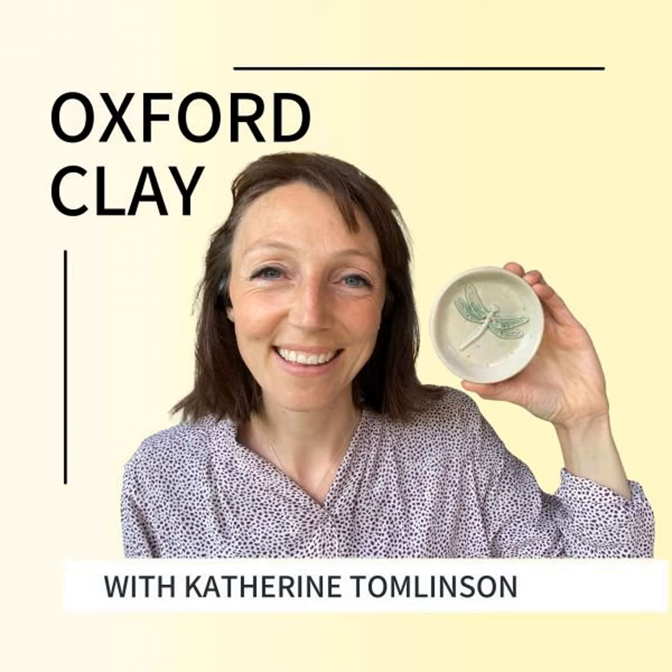Then you can pour the slip in and pour the slip out again. The way slip molds work, I've just realized I haven't really talked about that, is you pour the slip in and you wait for a certain amount of time. You can cast in all different clays: earthenware, stoneware, porcelain. Some clays will be very quick to cast. Bone china, for example, I don't use it, but that'll be very quick. It only takes a few minutes to cast. Other clays like stoneware clay, which I cast in, take a lot longer, up to 45, even 50 minutes.